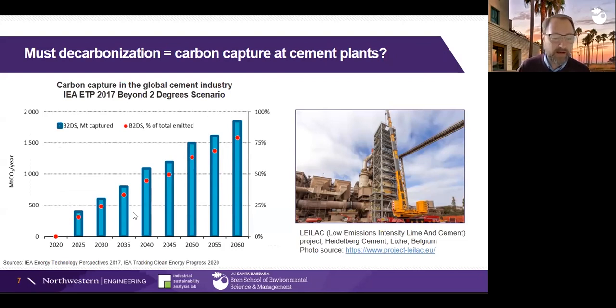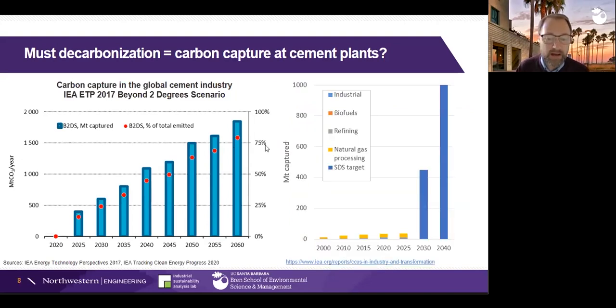What we see here on the left are results from the IEA's ETP 2017. The blue shaded column shows the amount of CO2 that's captured in the Beyond 2 Degrees scenario. This is a scenario that gets the world to net zero around 2060 and hits a warming target of around 1.75 degrees Celsius. It's clear that lots and lots of CCS must be deployed. If we look at the red dots here, which show the percent of total emissions that must be captured, that's around 80%. We quickly realize that what this implies is that most of the world's cement plants will need to be equipped with CCS. And the world is working on this.